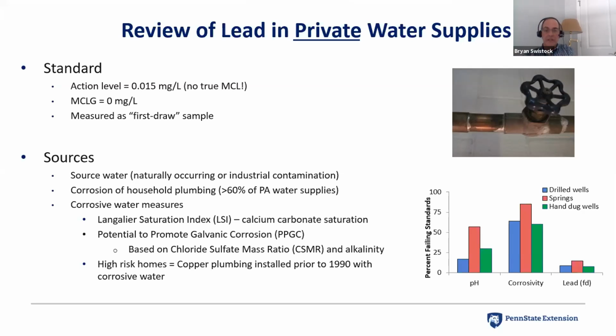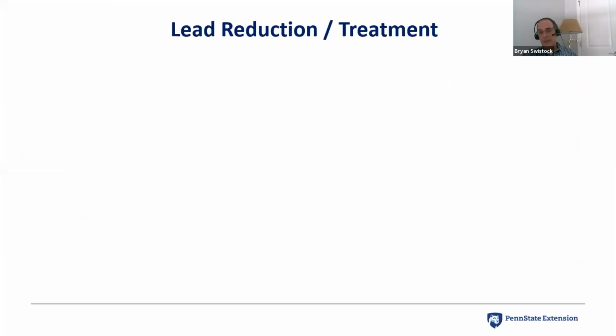We often throw around 1990 as kind of a cutoff because we found that a lot of those materials were still used for a while. Even after the regulations took effect, plumbers were still using up old stock of lead solder. And so we often use 1990 as kind of a cutoff, where if a home was built prior to that and it's got solder in it, there's a very good chance that that solder is going to have lead. Lead also being in fixtures and faucets continues to be a problem, even in relatively new faucets. And we can talk more about that here in a moment.